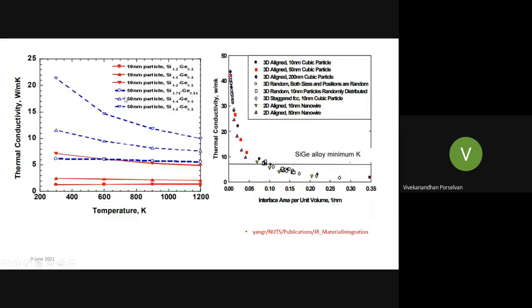And this is the thermal conductivity reduction in the silicon germanium alloy when it has different kinds of grain features, synthesized via different kinds of routes. Okay, so if you look at this particular silicon germanium which has 10 nanometer inclusions, we can see the blue color plots showcasing 50 nanometer particles in the silicon germanium alloy as an inclusion.